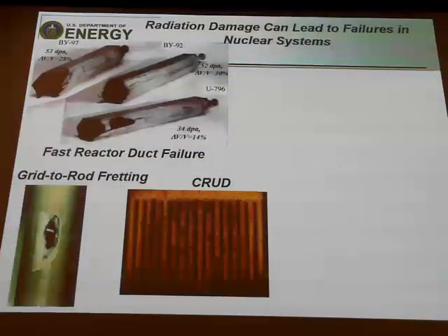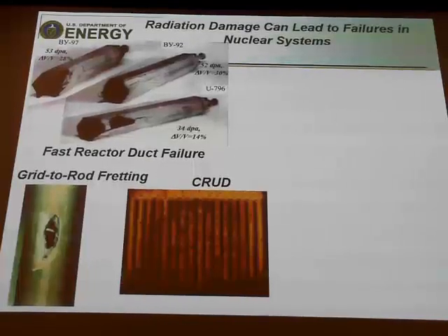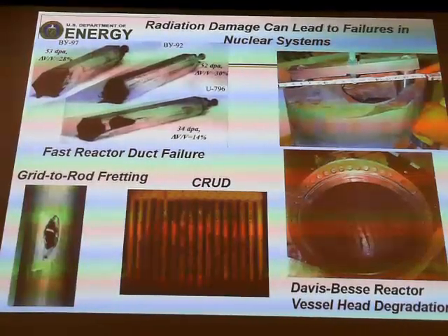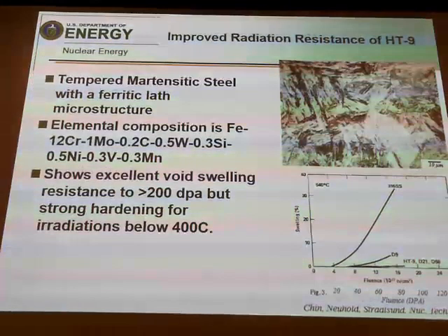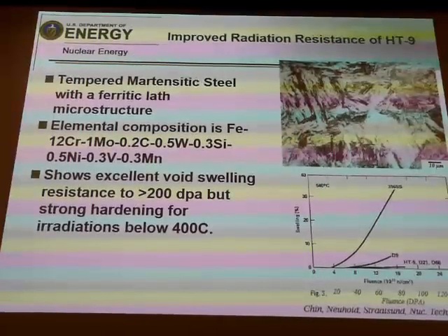And then with corrosion, there's significant things that can happen with the Chalk River Unidentified Deposit, or crud. It's identified, but anyhow, crud in the reactor, which isn't good, or corrosion in the head of a reactor that's accelerated by radiation. So these are things we want to avoid, so we want to try and develop better, more radiation tolerant materials. I'm not going to tell you that these materials apply to all those applications, but there are specific high dose applications like cladding material that this material would apply well to.